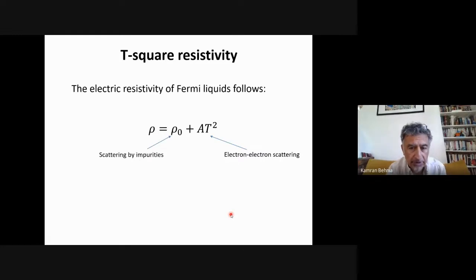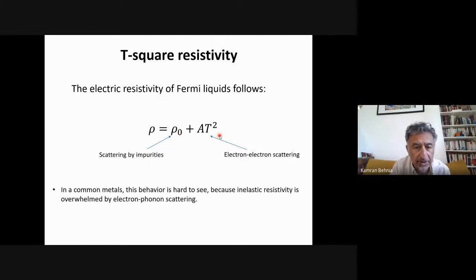So here is the starting point. The theory of Fermi liquid tells you that if you measure the electrical resistivity of a simple metal, you expect to have a first term, which is the residual resistivity. It depends on how clean your sample is, so scattering by impurities. And there's a second term, which is electron-electron scattering, which gives you T-square. Now, you may also know that if you want to look at this T-square resistivity in copper or in gold or in alkali metals, it's very hard to see it. This is because you have strong electron-phonon scattering.